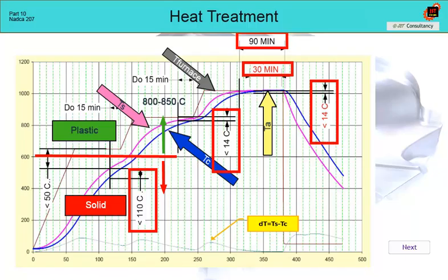Even if the entire heating process takes place under conditions that are not simple, a correctly modeled control system allows the entire process to be carried out completely automatically and without operator intervention. Moreover, completely independent of the size of the part. This is very important because it is the human factor that introduces errors into the system. Furnaces that do not allow temperature control from batch thermocouples should not work in the NADCA 207 system, and such furnaces should be clearly excluded from the system.